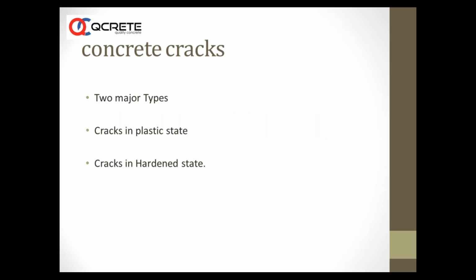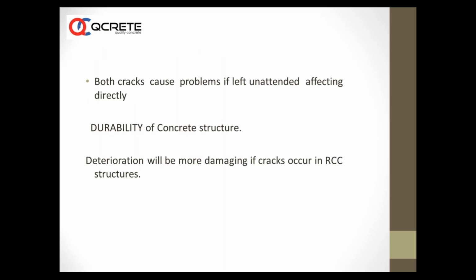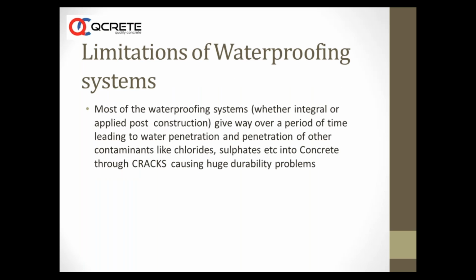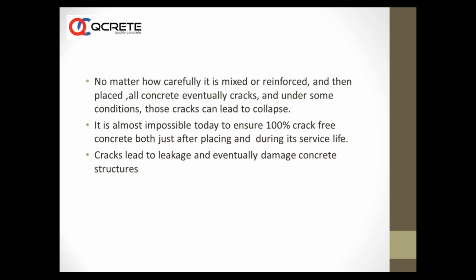two major types of cracks, cracks in plastic state and cracks in hardened state. Both cracks cause problems if left unattended, affecting directly the durability of concrete. You have a lot of waterproofing systems actually, and these waterproofing systems give way over a period of time, leading to water penetration and penetration of other contaminants like chloride, sulfates, etc. into the concrete through cracks, causing huge durability problems. No matter whatever you do, the cracks can lead to collapse.